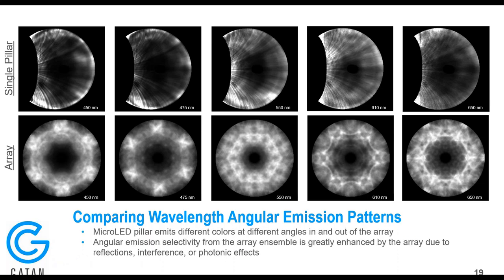What we can say, though, is that the micro LED pillar emits different colors at different angles, depending on whether it's in or not in the array. The angular emission selectivity from the array ensemble is greatly enhanced by the array, both in intensity and in directionality, due to either reflections, interference, or photonic effects, or some combination of those things.